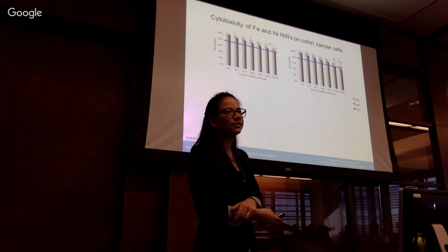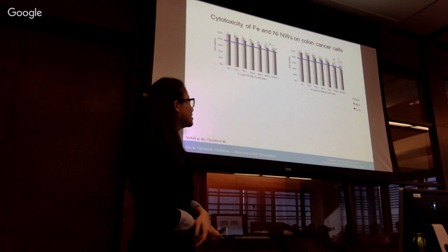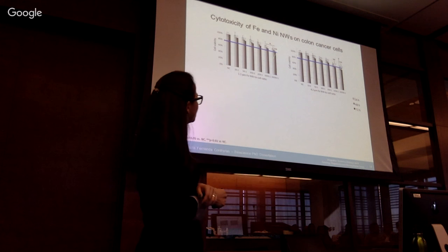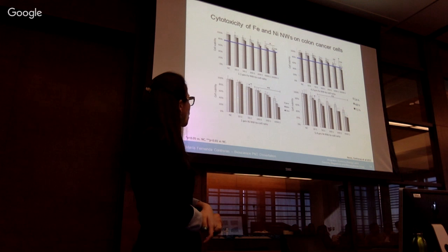Only for the higher incubation times and concentrations, the signal drops a bit below 80%, but not significantly. I mean, significantly with respect to the control, but not compared to, for example, the shorter length. These are the results for nickel. 1 micron, 5 micron. Experimental conditions were the same.